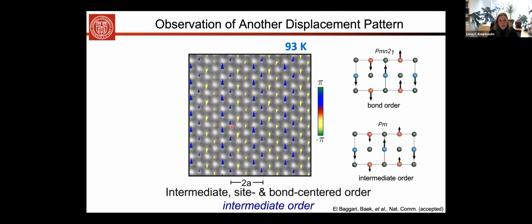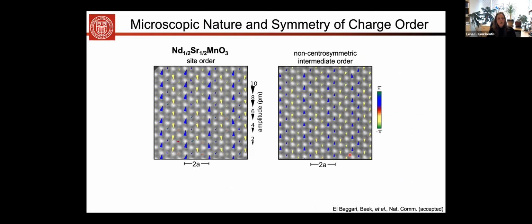And that brings us to a predicted intermediate phase, the intermediate ordered phase that has different symmetry, which now is distinct from bond-centered order, with a displacement pattern that is down, down, up, up. However, the amplitude of the modulation is different in the 2 atomic sites. So what we have discovered using cryo-electron microscopy in real space is that there are also areas in the film where this intermediate order is stabilized. So if you look at both, then we have site-centered symmetry in parts of the sample and intermediate order in others. And this is important because this is non-centrosymmetric, so you can start thinking of coupling to this in the future.